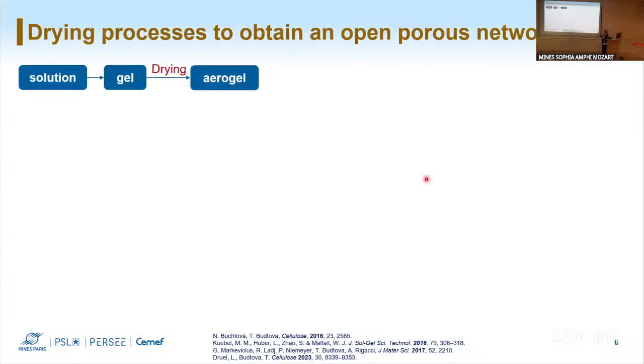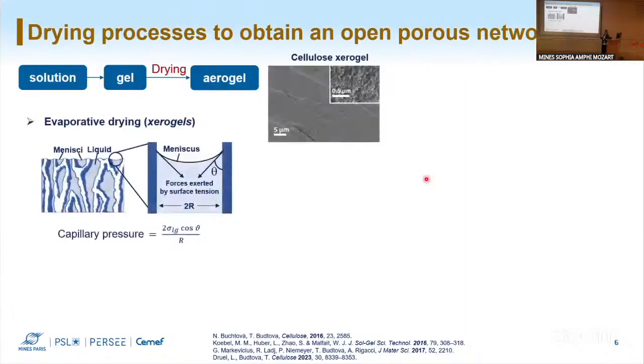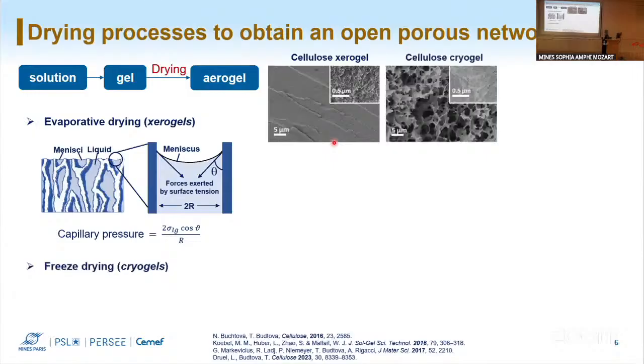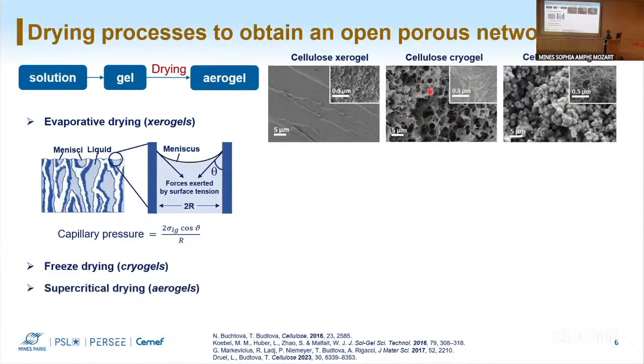Next, a very important parameter for aerogel materials is the drying technique that we use to obtain the structure. We start from a solution in general for aerogels, creating a gel and then drying to obtain the final aerogel. We can use evaporative drying. In this case, we have huge capillary stresses on the walls, and then we obtain very dense structures like this. We can use freeze drying, where we freeze the solvent and sublimate from the pores of our gel. And in that case, because usually water is used as solvent, the ice crystals that grow lead to these big pores inside our material. Lastly, we have supercritical drying, and we refer to these materials as aerogels in this thesis.